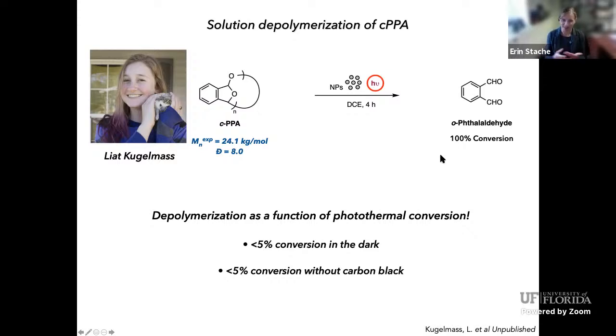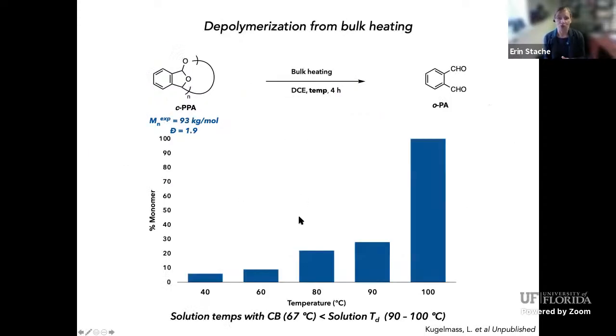We did some control experiments, as you might expect, and there's no conversion in the dark and there's no conversion without carbon black. So even though these red lights get kind of hot, they're not getting hot enough to do solution depolymerization of the polyphthalaldehyde in the absence of carbon black. But we did want to compare the kinetics of depolymerization as a function of photothermal heating versus bulk heating. So we just took the polymer and heated it up in solution, in the absence of carbon black. And what we found is that once you get above 90 degrees C, that's when you actually start seeing solution phase depolymerization. And once you get to 100 degrees C, after 4 hours, it's completely depolymerized, although not cleanly. There's definitely some degradation of the monomer in solution.